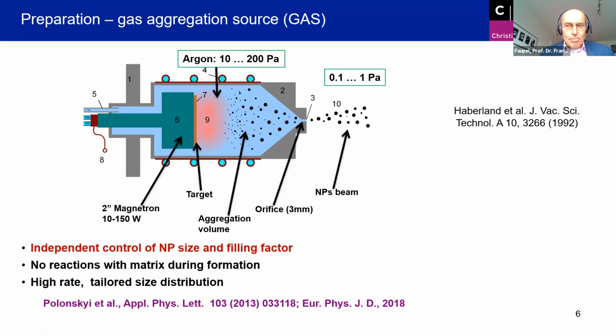That is our typical approach, which, as I mentioned, allows independent control of particle size and filling factor. We can also avoid reactions because we form the particles in an inert gas atmosphere. And we can also tune the gas sources to have quite high deposition rates, up to microns per minute. So that's also interesting for applications.